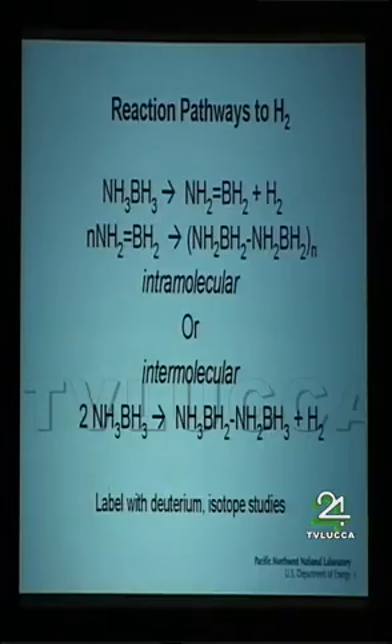So when you start digging through the literature to find out how hydrogen's released from this, there are probably about a half dozen papers, and 5 of those papers say it goes by intramolecular or unimolecular dissociation reaction, which is a bit surprising because when you first look at this and you have these hydridic and protic hydrogens that are interacting with each other, you might think it would go by a bimolecular